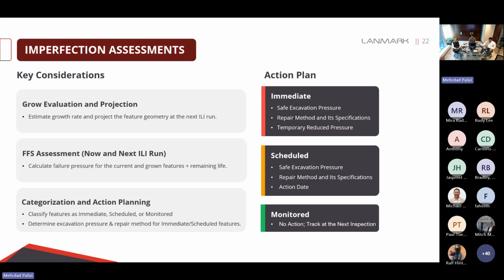So there's some consideration when we are performing imperfection assessment. Here I have 3 notes that I go through one by one. The first thing is we are not assessing features only in their as-found condition. There's some features that are time dependent, let's say corrosion. For these features, it is important that we have an estimation of the growth. This could be done by reviewing the historical ILI data. We might also do a literature review and come up with a conservative value. After we figure out what is the growth for each one of the features, we should project them to the time for the next ILI inspection.